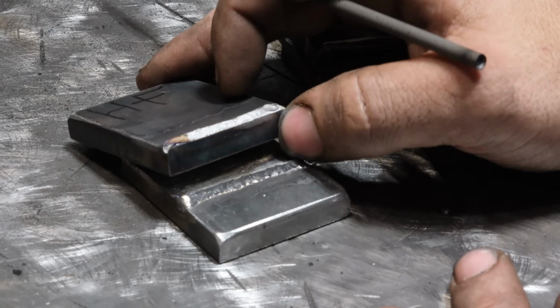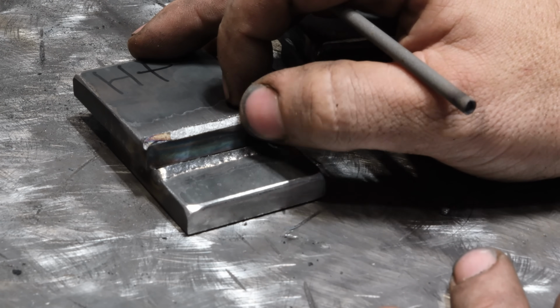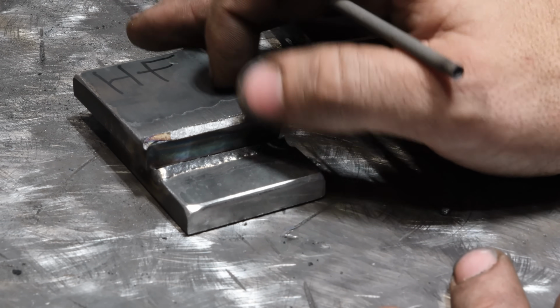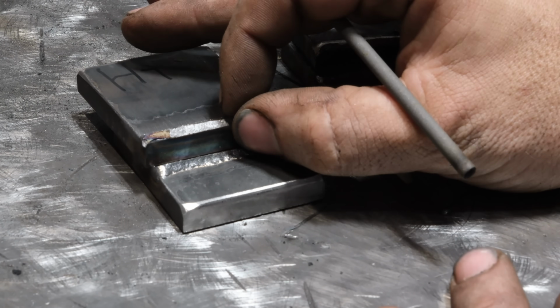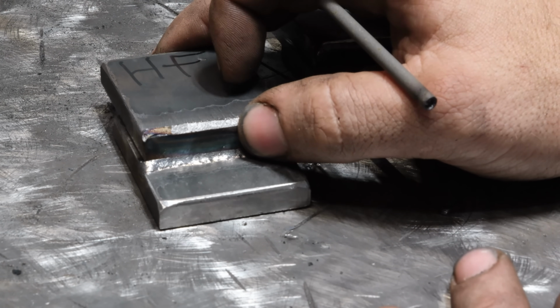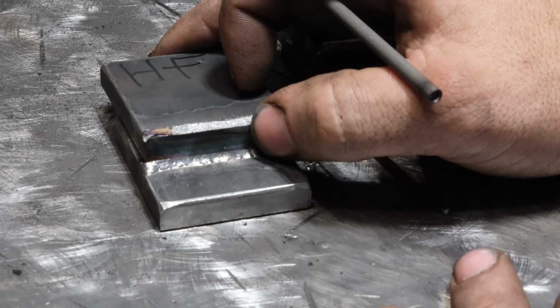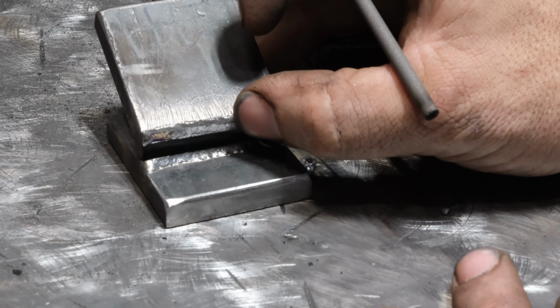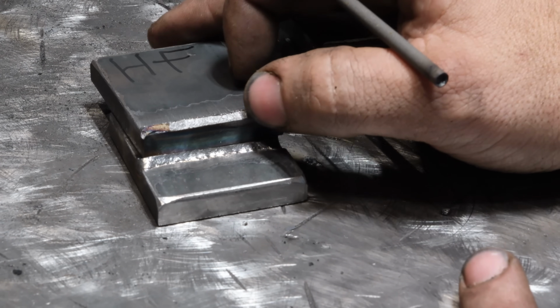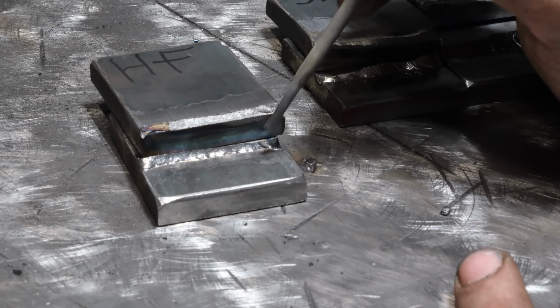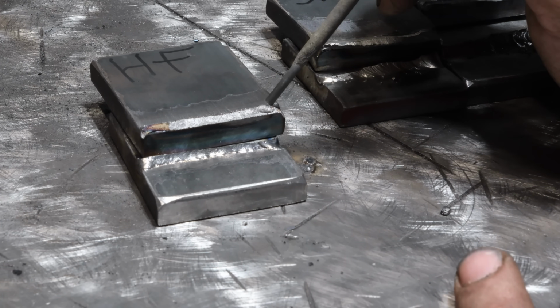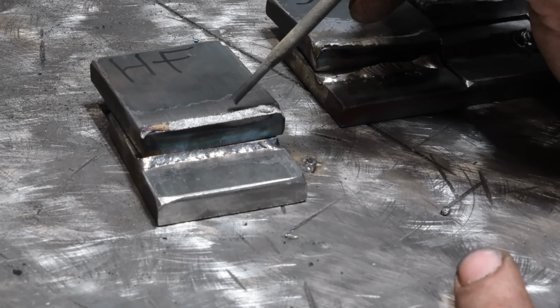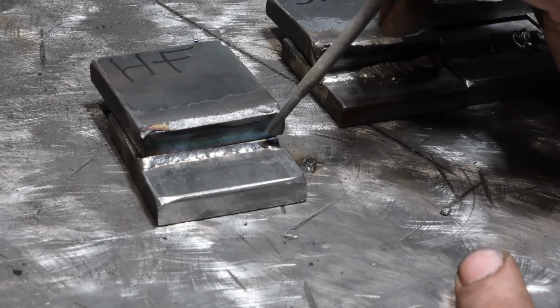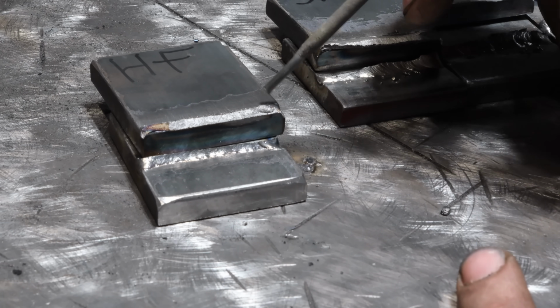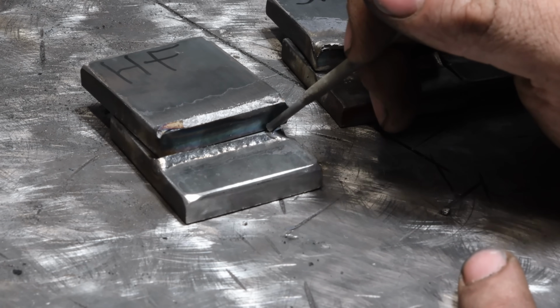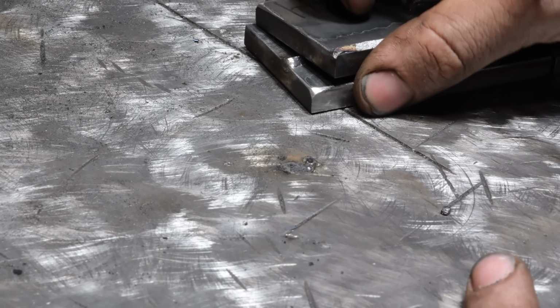Now this rod did actually have some penetration. It did break down almost the complete edge of the plate. Very thin throat depth of the weld. Had I done multiple passes, it wouldn't have been any better, I can tell you that. So very brittle. But again, this particular rod is really meant to do a single pass on something, and it's not designed to be layered, and it's just meant to be hard and wear really well like iron. So it excels at that, but it definitely does not excel at joining 2 pieces of metal together. But it was no doubt the worst break test I've ever seen on this channel, so don't use it.